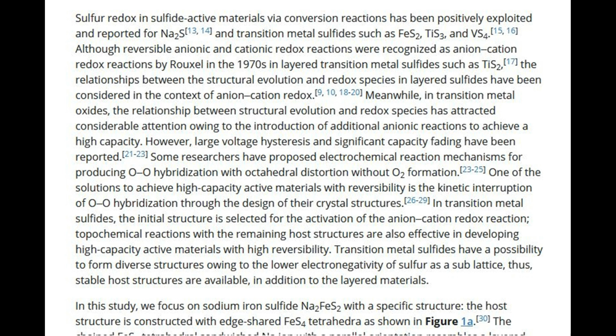26-29 In transition metal sulfides, the initial structure is selected for the activation of the anion-cation redox reaction. Topochemical reactions with the remaining host structures are also effective in developing high-capacity active materials with high reversibility. Transition metal sulfides have a possibility to form diverse structures owing to the lower electronegativity of sulfur as a sublattice, thus, stable host structures are available, in addition to the layered materials.